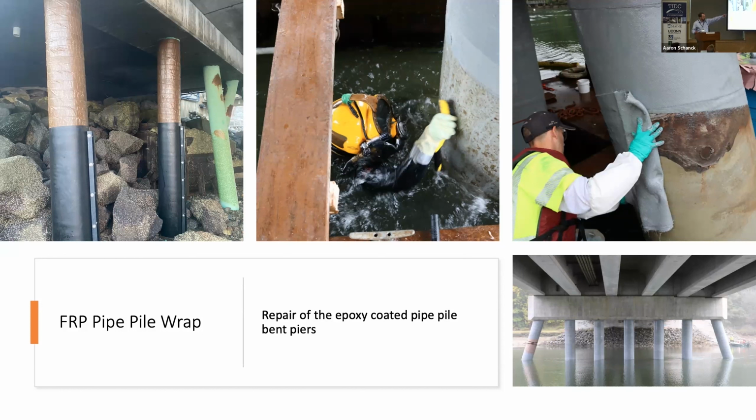So on the bridge over there we used a standard fiberglass mat that was infused with a pigmented epoxy that would cure underwater. So we used divers and we wrapped the piles with that, because in the tidal zone, the fusion bonded epoxy on the piles failed. The bridge is in beautiful condition, but you have a substructure element in tidal water where, in the tidal zone, its coating system was failing. So without any attention, you're going to have a bridge you're going to have to replace that was built in 1996 on Route 1 in York when everything else was beautiful.